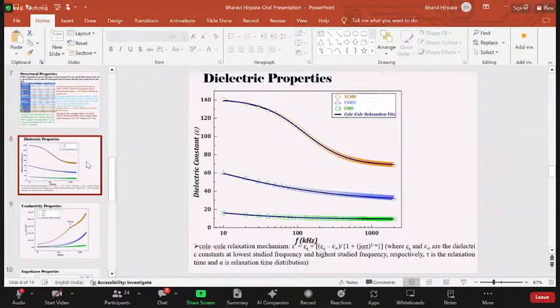We can also see here that for the YMO sample, the hexagonal structure supports non-centrosymmetry, which favors the ferroelectricity exhibited by hexagonal structured manganites. So in this context, we can say that YCMO should exhibit lower dielectric, since the YCMO structure possesses a dominant orthorhombic phase, that is 59% as seen in the Rietveld refinement, which is not favorable for non-centrosymmetric nature, so ferroelectricity as well as high dielectric. But our present study indicates some opposite nature of dielectric constant values, where YCMO exhibits larger dielectric constant as compared to YSMO.